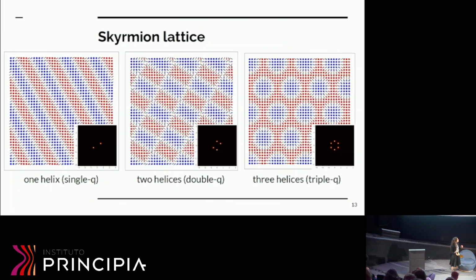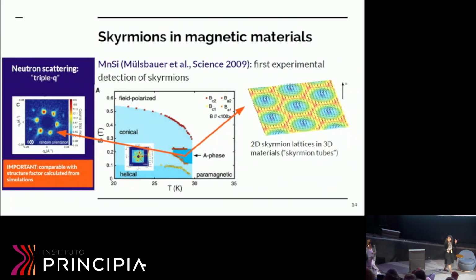And in fact, it is the way that a Skyrmion lattice was first measured a bit over 15 years ago in MnSi, where the magnetic moments are manganese. And so this is the magnetic field and temperature phase diagram. And so this thing, which is sometimes called the pocket of Skyrmions, is a region in temperature and magnetic field where they measured this pattern through neutron scattering, right? So this would be the smoking gun, that you have something like this Skyrmion lattice.